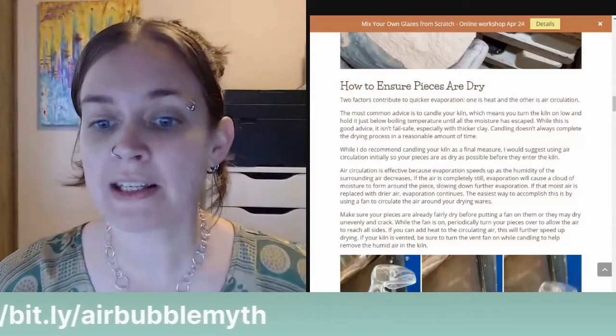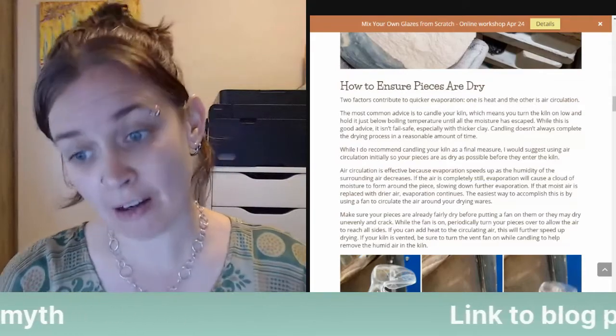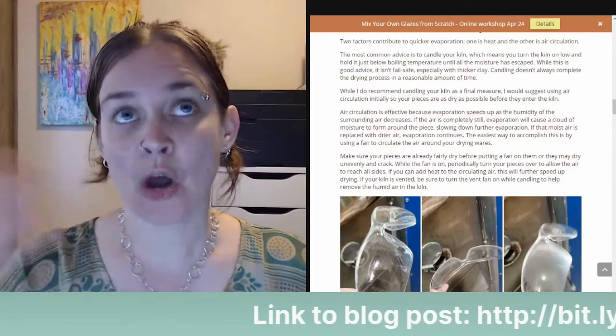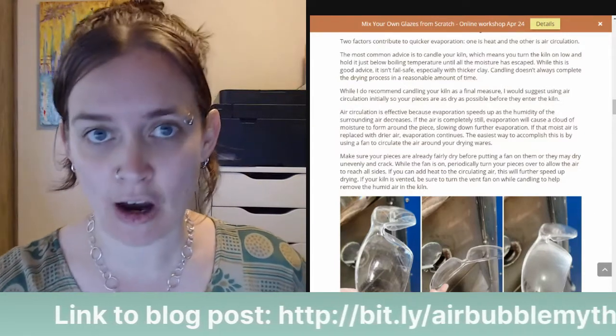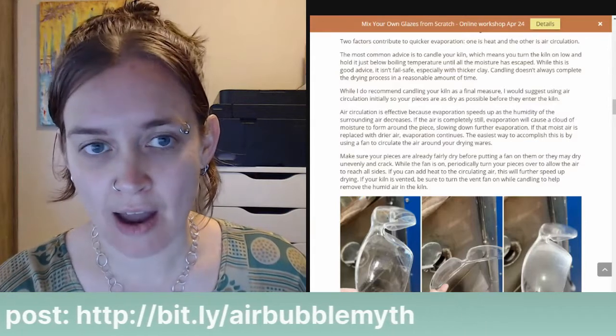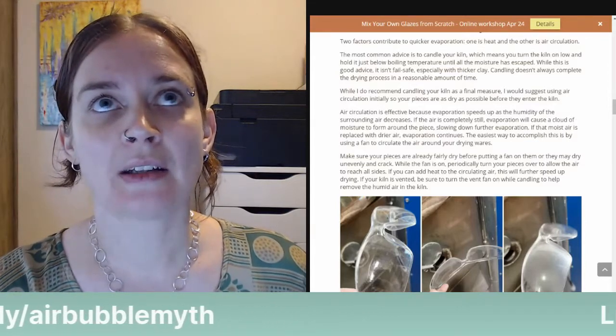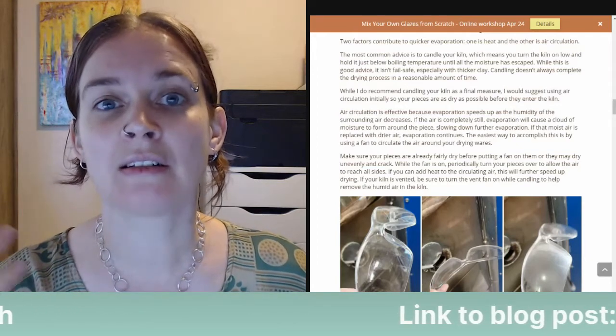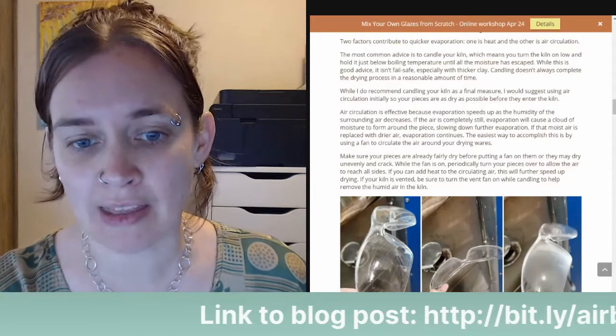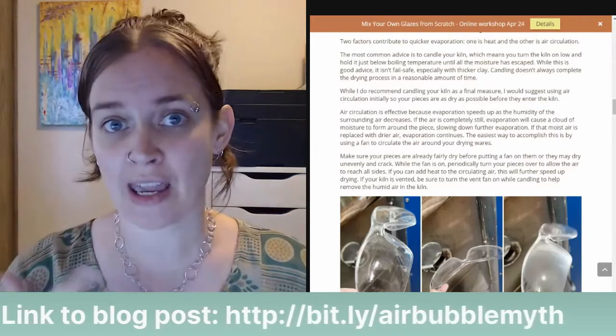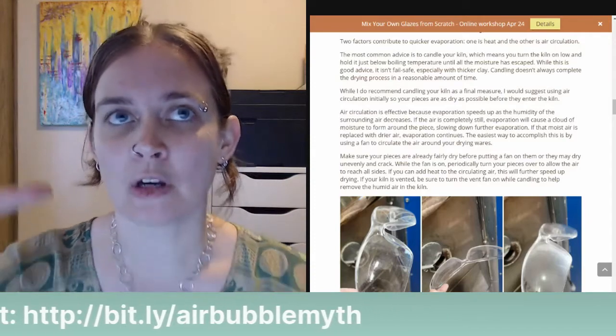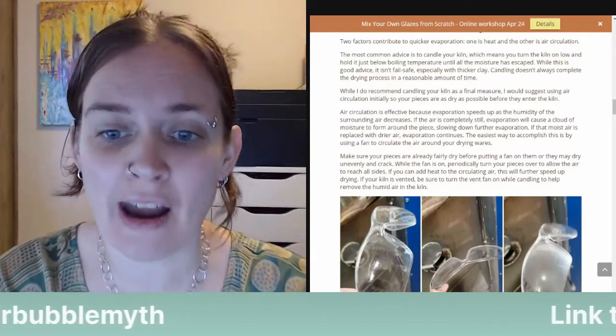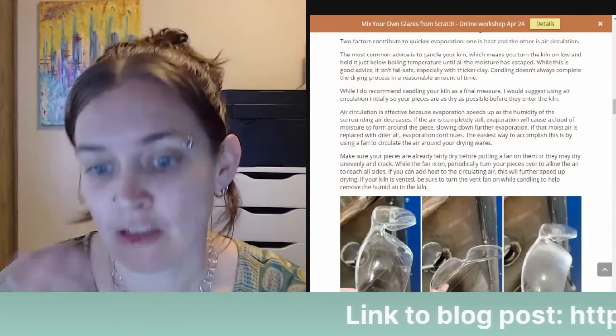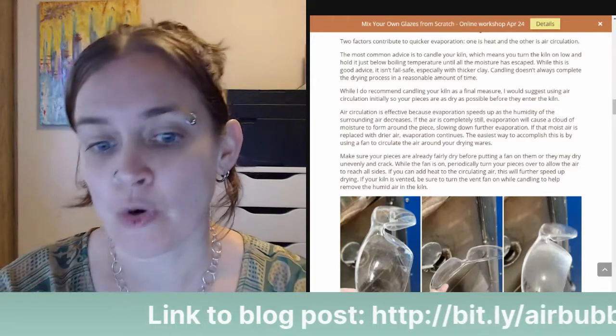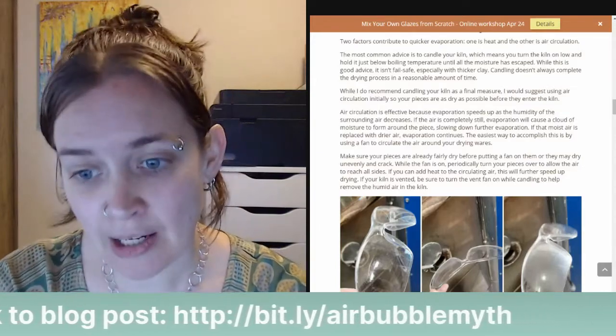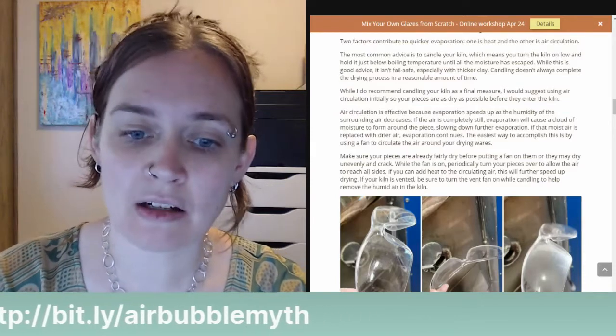So make sure your pieces are already fairly dry before putting a fan on them, or they may dry unevenly and crack. So I would always wait till past the leather hard stage, so past the point where the clay has stiffened up. And once the pieces are starting to look dry, then put a fan on them. You don't want to speed up the drying so much that your pieces shrink at different rates, and that's what causes cracking. While the fan is on, periodically turn your pieces over to allow the air to reach all sides.